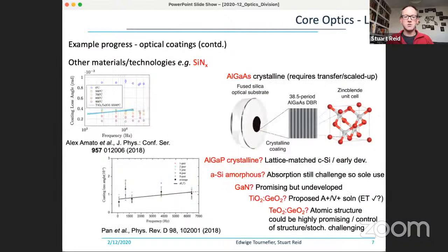There are other materials which are being considered. I'll just cite some work being done across Europe and within the LSC on silicon nitride, which looks like an attractive mirror coating. We also have, when we look beyond amorphous coatings, crystalline coatings. Aluminium gallium arsenide is one which is often discussed as being a really attractive technology, but it requires a substrate transfer from the gallium arsenide wafers that these coatings are epitaxially grown from, which could cause some challenges when we consider the level of scale up we require for ET.